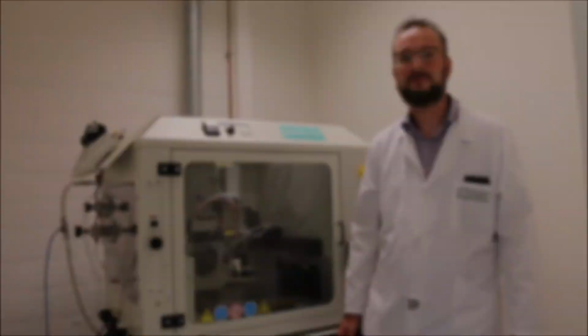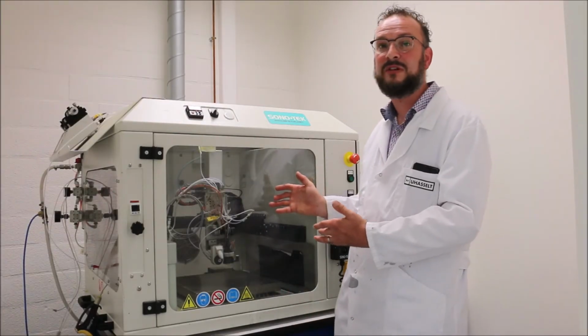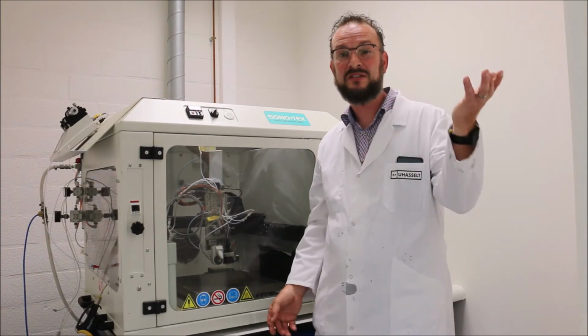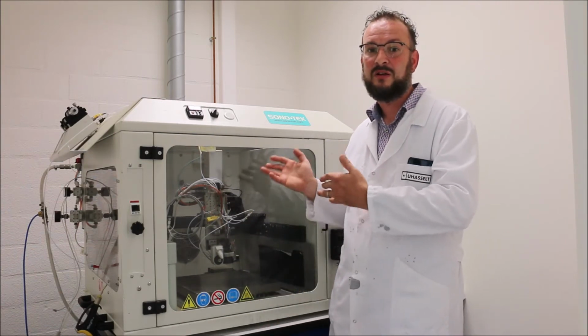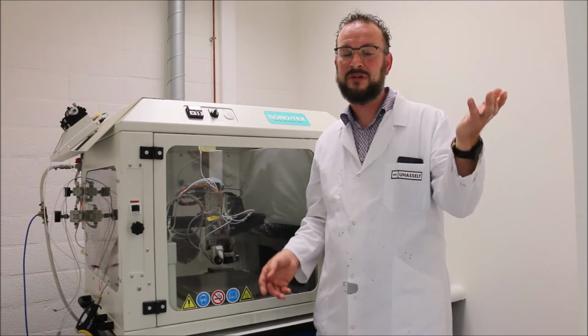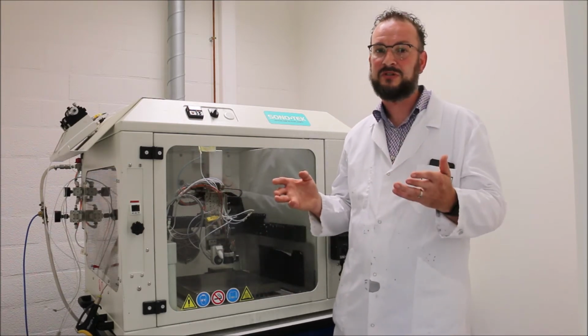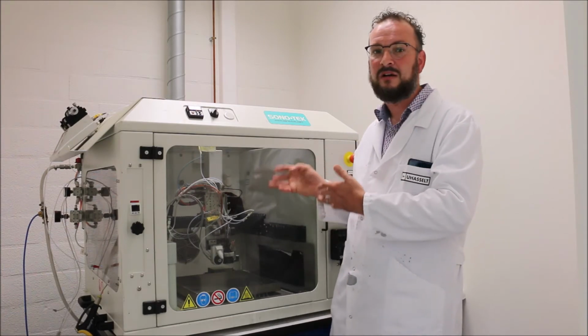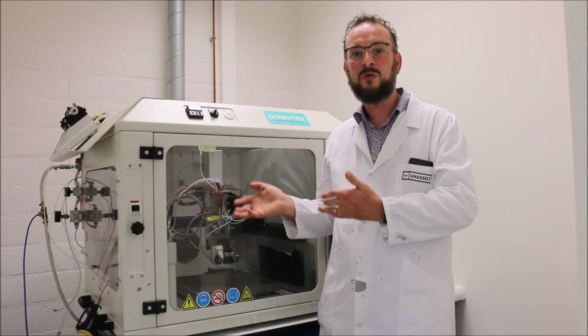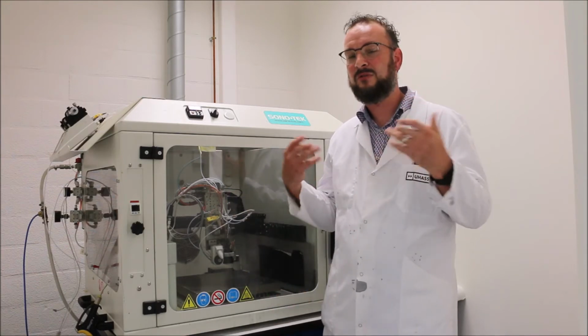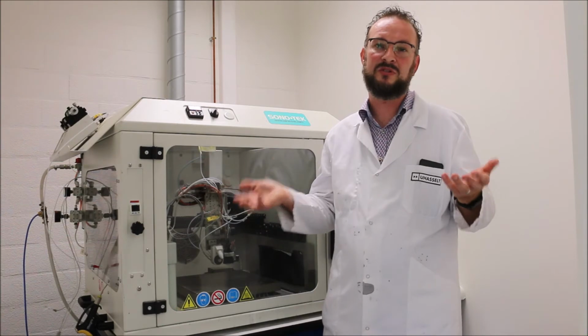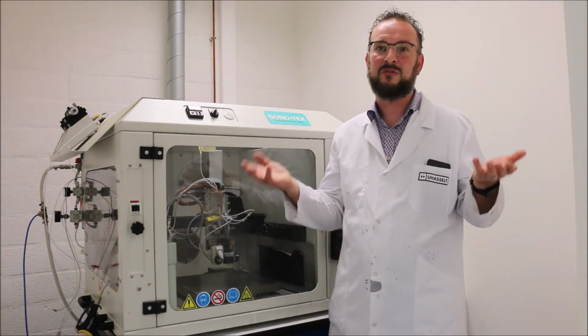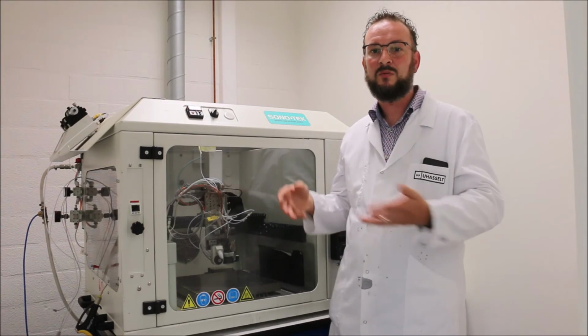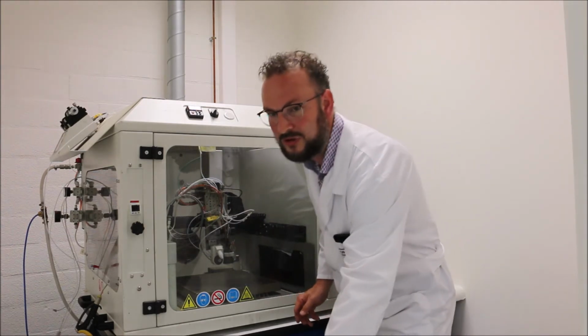The next printing system that I show you is ultrasonic spray coating. This is our ultrasonic spray coating system, and if you compare it to inkjet printing, this system can deposit coatings on large area, where with inkjet printing we focus on printing of structures. The coatings we deposit here are functional coatings having a thickness of only 20 to 30 nanometers. And if you compare that with the standard spray coating techniques used in industry, which have a thickness of around tens of micrometers, you know why we need a lot of research to develop these functional coatings.